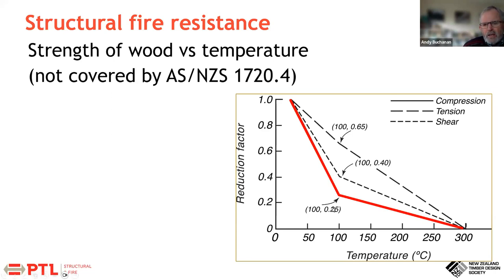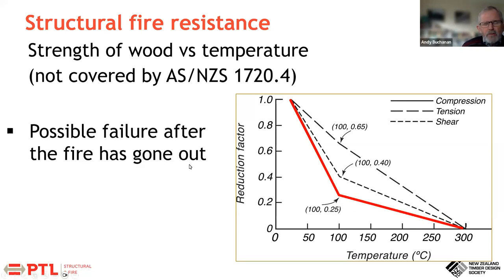And what that is showing us here is that if the wood just gets up to 100 degrees, nowhere near 300, long before it starts to char, it only has a quarter of its compressive strength. This is how the furniture makers do steam bending of wood. They put wood into a steam bath, they heat it up to 100 degrees, and they can bend it because you have compression yielding on the compression side. And so this is a bit of a worry, because it does mean there's a possible failure after the fire has gone out.